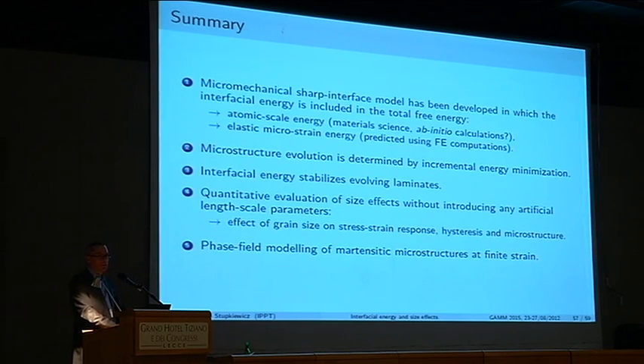I have also shown you that the interfacial energy does stabilize the evolution of laminates, which are otherwise unstable, and we have some quantitative evaluation of size effects without introducing any artificial length scale parameters. In particular, we could derive some kind of grain size dependence of the macroscopic response.